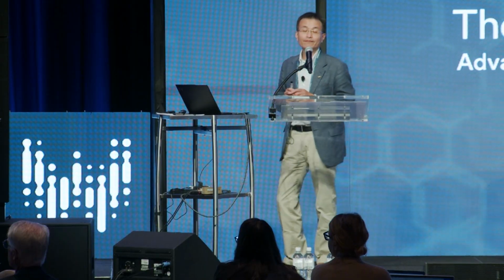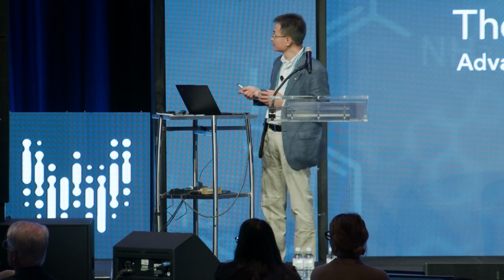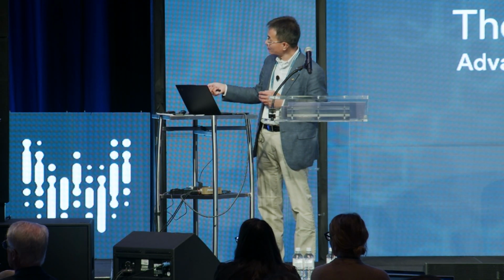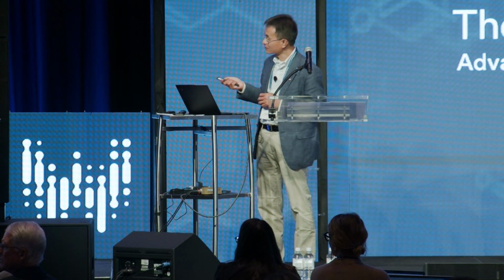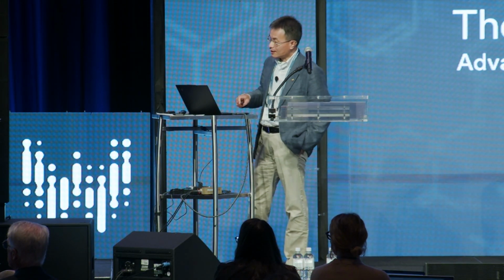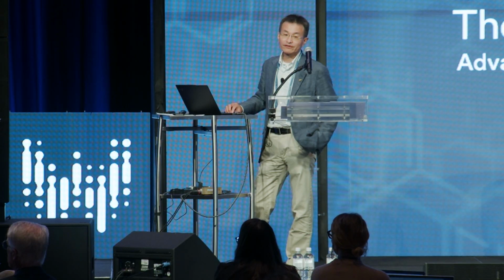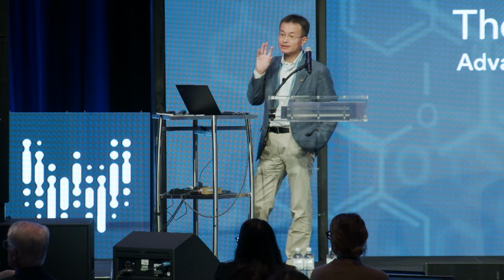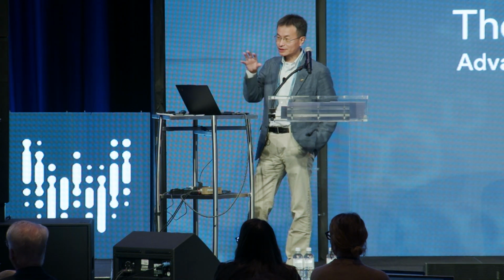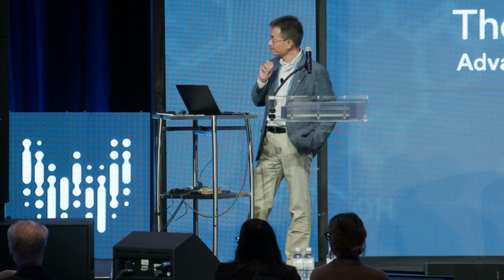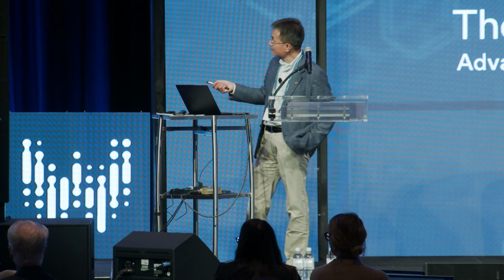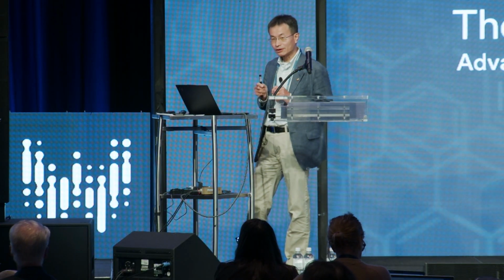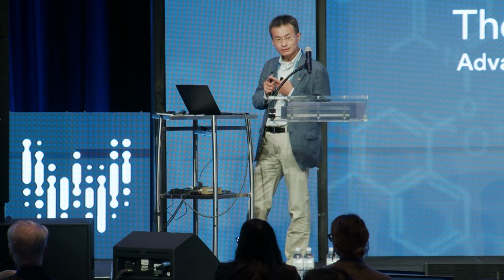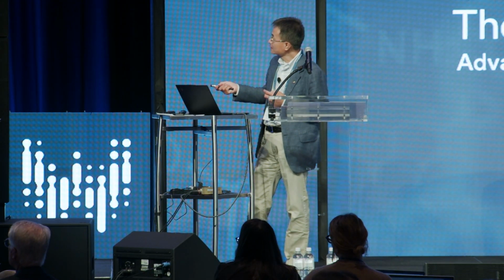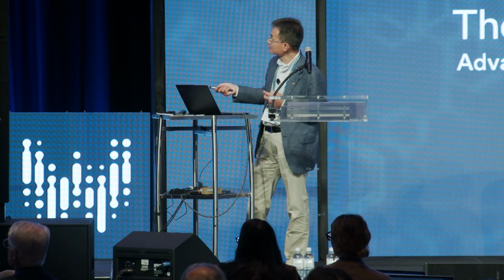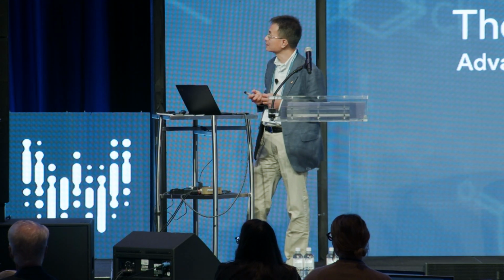When I talk about nanowire growth, I normally go back to a relatively old Bell Lab work by Wagner. This is back in the 60s. Back then, Wagner at Bell Lab was developing a growth methodology to grow ultra-pure silicon and germanium bulk single crystals, just like Steve mentioned during the noon talk. At that time, Wagner developed the so-called vapor-liquid-solid crystal growth methodology, and he used it to grow silicon and ultra-pure germanium. You can see in this image the scale bar is millimeter scale. It's a very big single crystal.